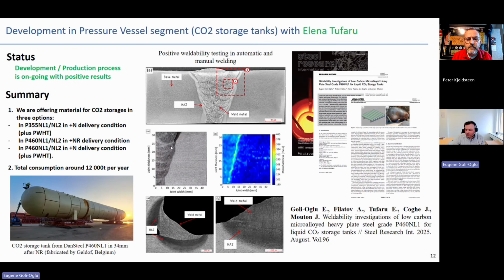Here below you see a part of the weld and a part of the base structure, and the colors which we are getting from the micro hardness measurement, which makes a lot of dots like needles, in a matrix, showing us a more dynamic picture with high resolution, I would say, of where we could have a potential problem or not. If the hardness level is reaching above 300 Vickers, then it's a question for discussion and how to use this material. But if it's 250, 260, depending on the material, then it's a reliable weld.